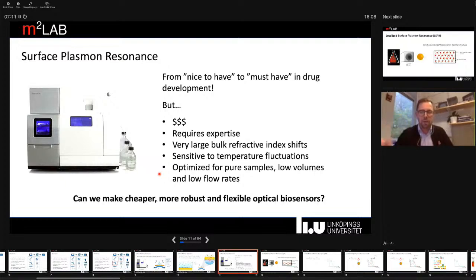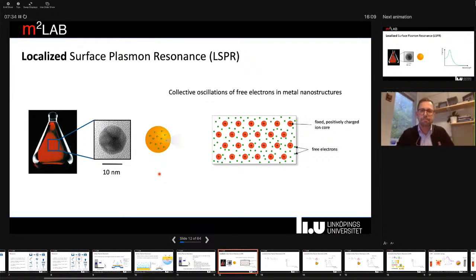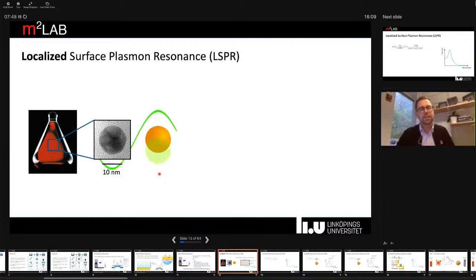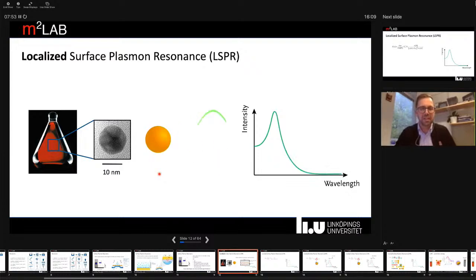But what my research is about is essentially to see if we can make cheaper, more robust, and flexible optical biosensors with similar performance as you can obtain from surface plasmon resonance based transducers. And this made us look into the field of localized surface plasmon resonance. So essentially a very related phenomenon to SPR, but using metal nanostructures instead. When having metal particles that are small in size, and small typically means less than 100 nanometers, then we can much more easily induce collective electron oscillation. Essentially, we don't need any complicated optical setup to do this. So we can just irradiate the particles and we induce these collective electron oscillations, which results in a lot of absorption of the visible light as well as scattering.